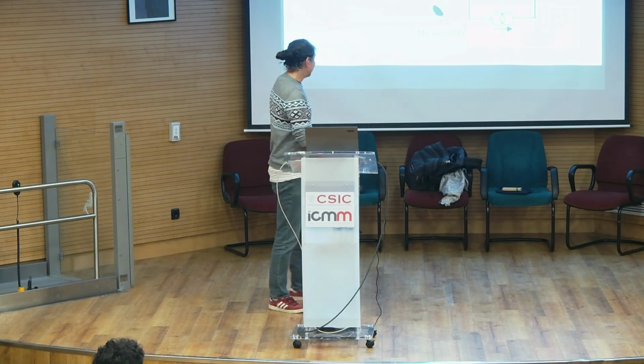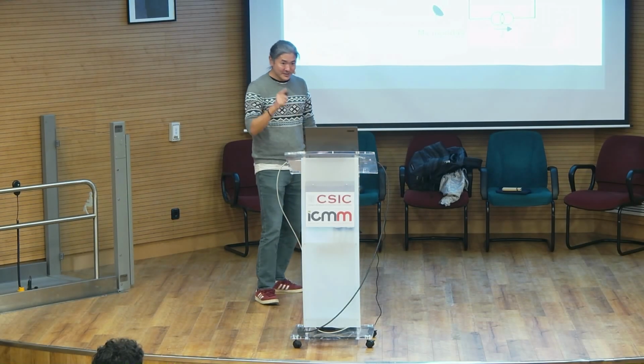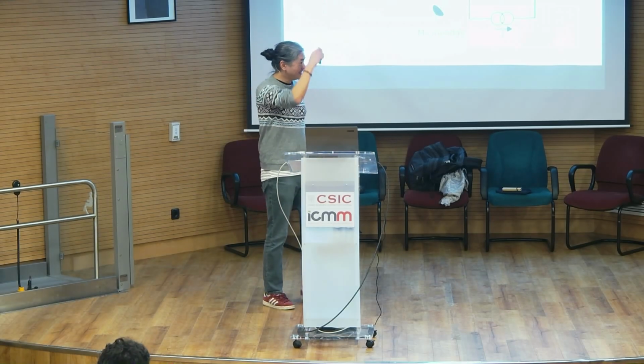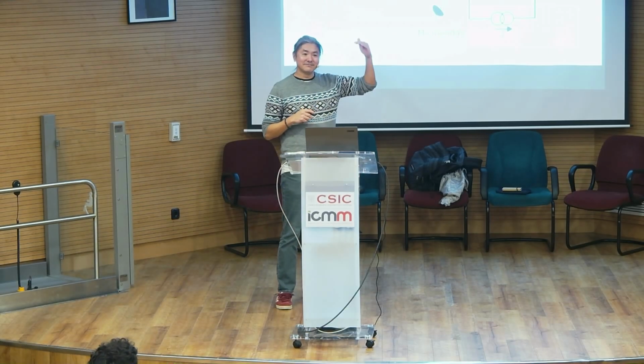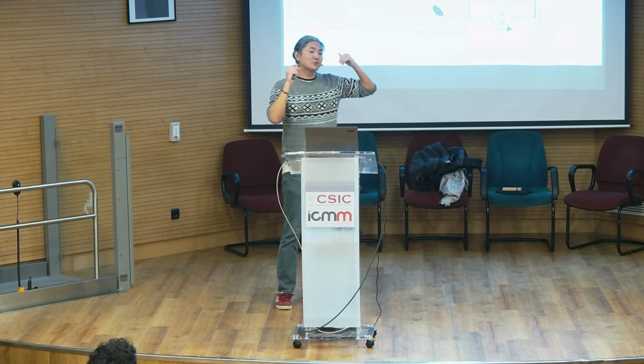Okay, so I have a device. It has a given cooling power, which is not high because we're talking about low temperature, so all heat dissipation mechanisms are suppressed. Parts of the system are superconducting, so they cannot carry heat. But parts are normal, so this is what actually carries the heat out. So then it would depend on whether the switching current of my weak spot is higher or lower than this cooling. There's a threshold current below which I have enough cooling power and above which I don't.